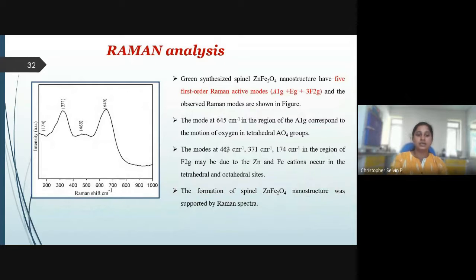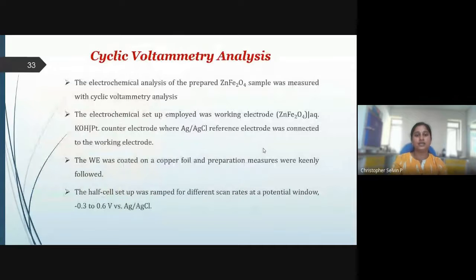So this is the picture obtained for zinc ferrite nanostructure out of Raman analysis, which shows 5 first order Raman active modes, 1 A1g, Eg, and 3 F2g modes, and the corresponding index is given in these discussions. So the formation of spinel zinc ferrite nanostructure was supported in this picture. Followed by that, we have electrochemical analysis by means of cyclic voltammetry.